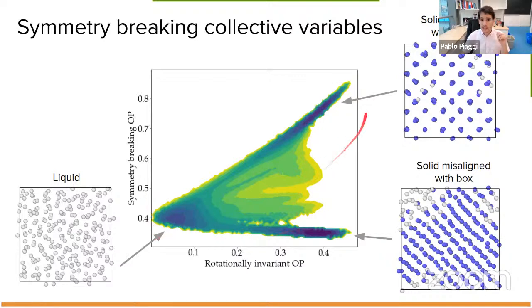And the free energy landscape that we see here has the liquid in this region, that is when both order parameters have low values. And for large values of the rotational invariant order parameter and low values of the symmetry breaking one, we have solids that are misaligned with the box and therefore will have defects or residual stresses, for instance. And instead, when both collective variables increase simultaneously, we have the solid that is well aligned with the box. That is typically what we try to get because this will have no defects and no stresses.